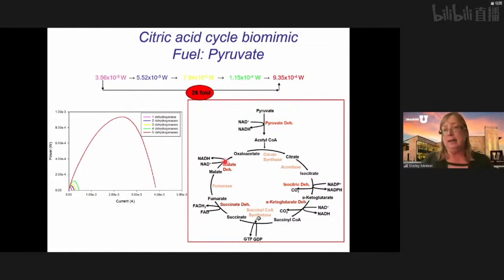It was just naive of us as electrochemists to not fully understand the biological system. So unlike a chemical system, biological systems have built-in metabolic control. And that built-in metabolic control means if you build up any one of these intermediates, that intermediate will actually inhibit previous enzymes of the cycle. So in order to keep metabolism from going awry and keep life functioning, the metabolic systems have this built-in control where all of the intermediates inhibit other enzymes of the pathway in order to maintain that control. And so if we start to make an artificial pathway that doesn't have the whole cycle, we build up intermediates, and those intermediates affect this initial enzyme, pyruvate dehydrogenase. And so it's not till we add the final enzyme and we have this cycle functioning that we aren't building up intermediates and we see higher current densities and higher power densities.